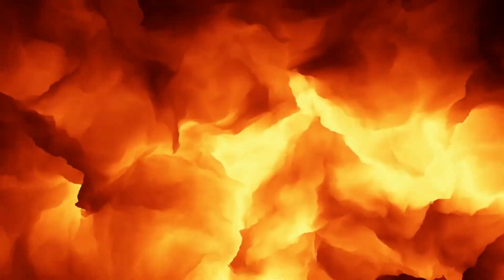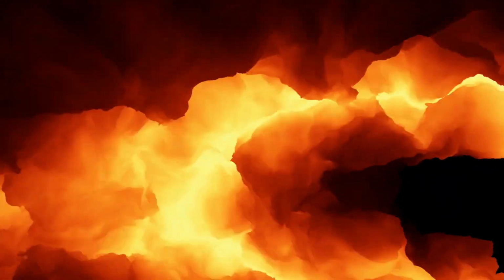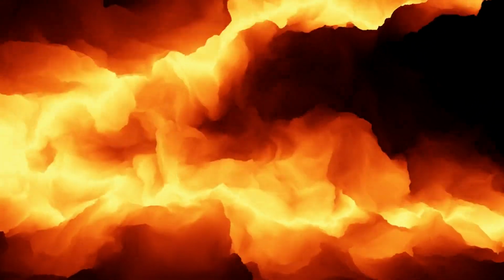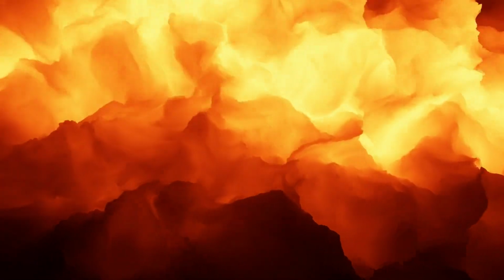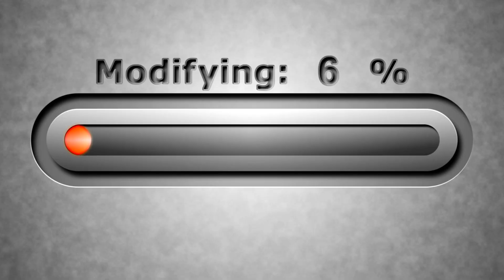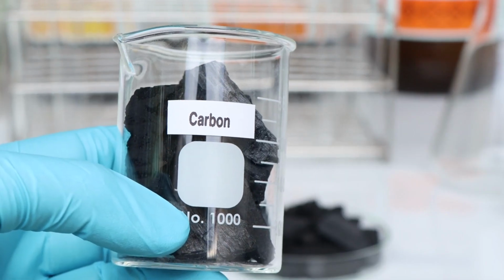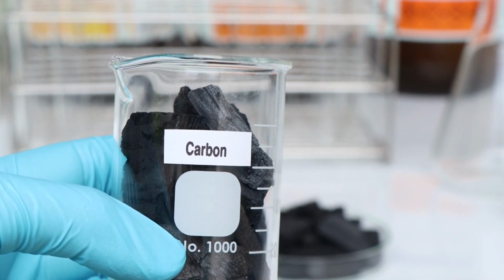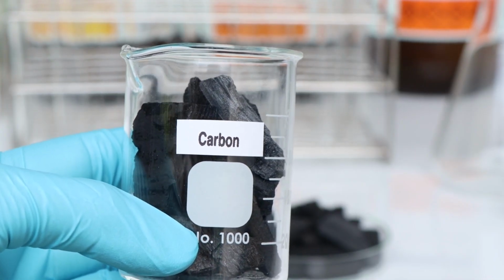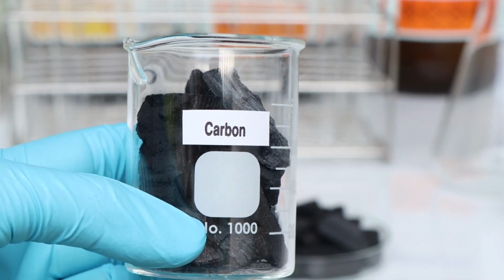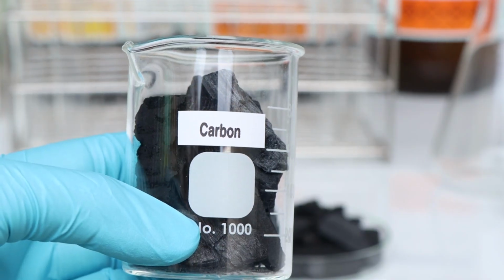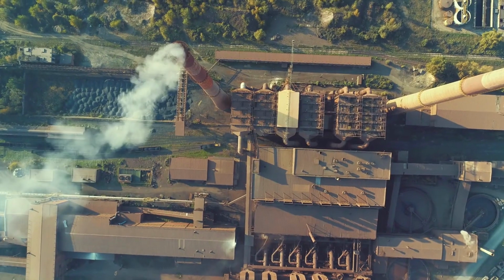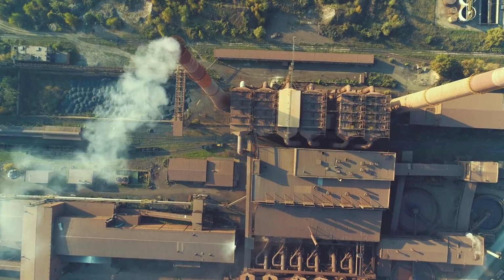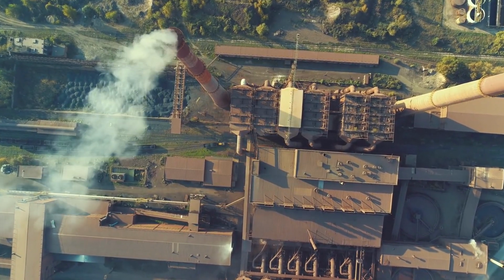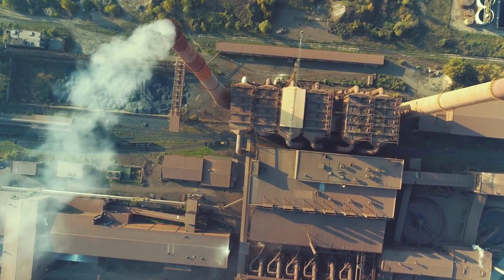The spectacle is intense. Bright white flames burst from the converter mouth, and sparks fill the air like a glowing storm. Within about 20 to 40 minutes, the entire composition of the metal changes. The carbon content drops from several percent down to less than 0.3%, and what remains is pure, refined steel, strong, flexible, and ductile. It's one of the most dramatic transformations in all of industry, from brittle cast iron to the powerful, versatile steel that shapes our world.